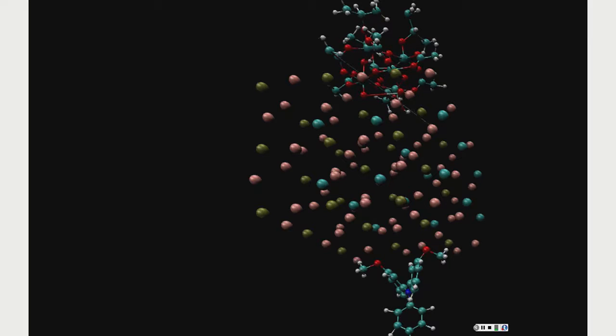But we understand that for those which are solid, this classical approach is okay, but the soft guys should actually be treated quantum mechanically. In other words, this energy should not be equally distributed over all atoms.